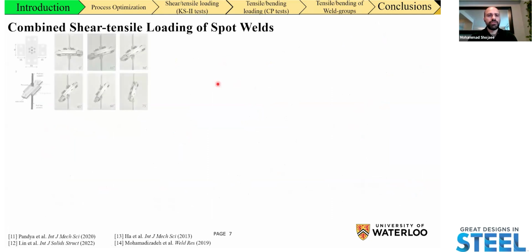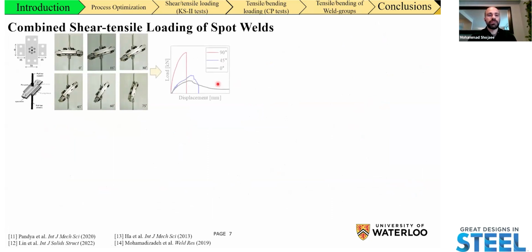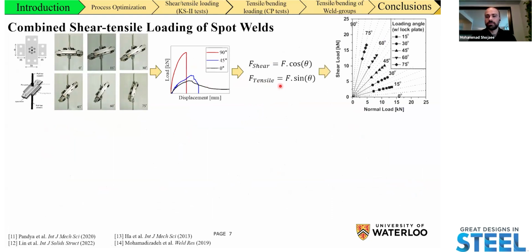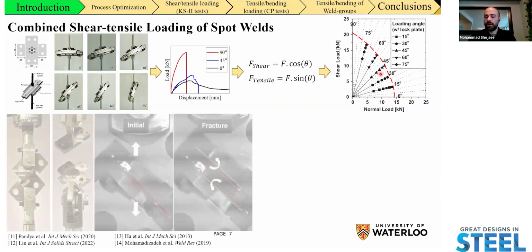Now, in terms of the combined shear tensile loading of the spot welds, we typically have a customized fixture that is able to accommodate different proportions of shear and tensile loads. And what we get from these tests is going to be load displacement curves at different loading ratios. These load components can be decomposed into their comprising components in terms of shear strength and tensile strength, and we can fit a curve through them to get our most accurate failure loci.